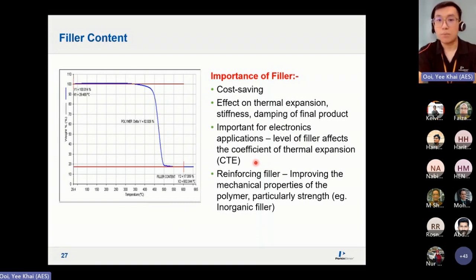Okay, so in terms of electronics, this is important because it affects the CTE. Okay, so for example, if you are using your phone or your electronics, sometimes you notice that it's getting hotter and hotter when it's running. So as what I've mentioned, material will expand, okay, when the temperature goes up. So they need to measure what is the coefficient of thermal expansion of the materials. If they expand too much, it's going to peel off or it's going to become concave, okay? Or you notice the swelling of the material. This is due to the CTE not being within the permissible value, okay?